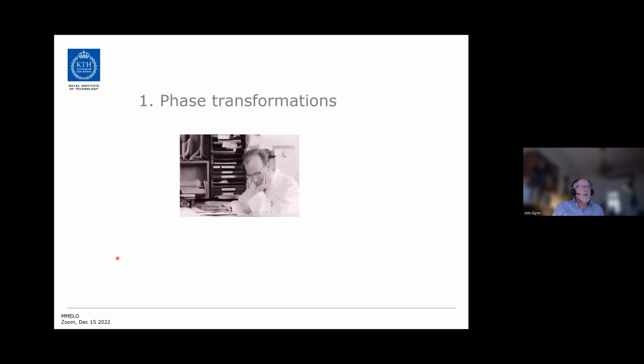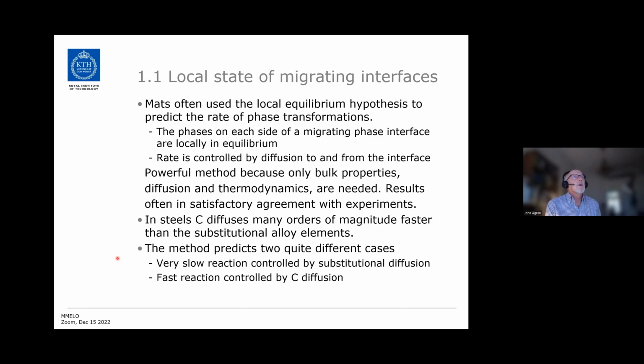So here is a young Mats studying phase transformations, I believe. So he often used the local equilibrium hypothesis to predict the rate of phase transformations. In that method, you assume that the two phases on each side of a migrating phase interface are locally in equilibrium, and then the rate is controlled by diffusion from and to the interface.